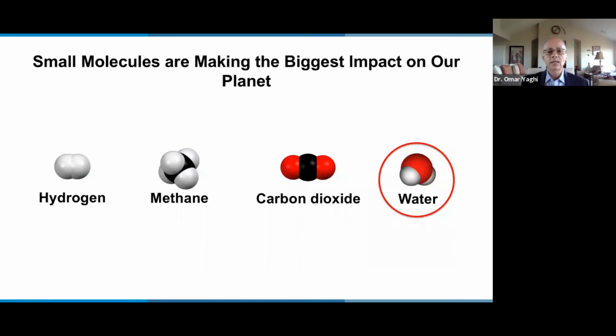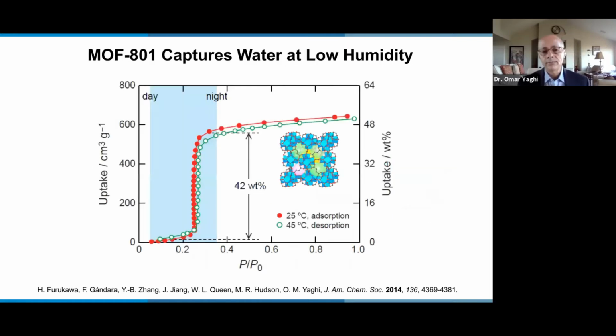So we've been investigating different gases, including carbon capture and methane and hydrogen, but today I'm going to focus on water. So we discovered and published this article back in 2014, that this MOF, it's a zirconium MOF, takes up water at room temperature or at 25 degrees in the red line. And the amazing thing is that we saw that it takes up water at low humidity. This is a humidity of around 20% relative humidity. That was unique. And what was even more unique than that is the fact that you can remove the water by just heating to 45 degrees C.